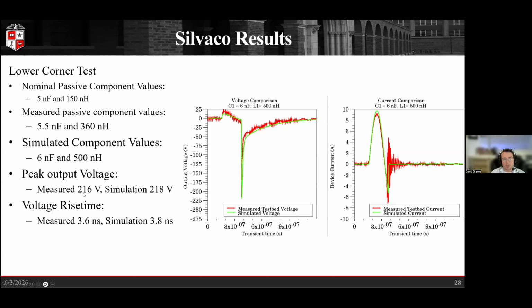Looking at the peak output voltage, our peak voltage measured 216 volts, whereas our simulation measured 218 volts. So again, a very good fit there. And our rise time, again, matched relatively well at 3.6 nanoseconds measured and 3.8 nanoseconds in simulation. And those are going to be our 10 to 90 rise times. And we can see on the current side as well, it matches extremely well, giving us the same characteristics, the same approximate amount of peak forward pumping current and our reverse pumping current.